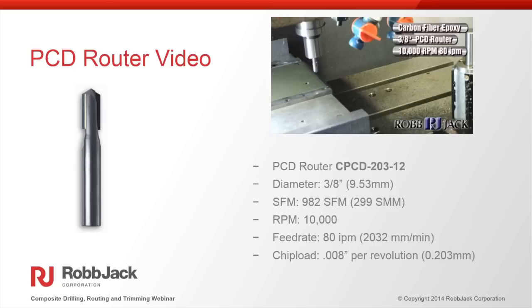A lot of times we have to recommend a little bit lower RPM, but then a lot of times faster feed rate. A lot of times people will be going 18,000 RPM with a 3/8 tool or 20,000 RPM, but then going like 20 inches per minute feed rate. So typically we recommend 10,000 RPM, anywhere between the 900 and 1,000 surface footage range, and about 80 inches per minute feed rate, which is about over 2,000 millimeters per minute. So the chip load is 8 thousandths per revolution.